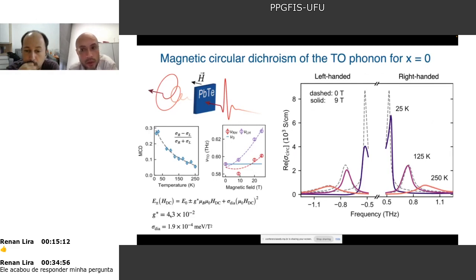So you can see here, still not very large, 4.3 times 10^-2, but much larger than the theoretical prediction from 2019 that I also showed you before. And here is the diamagnetic shift. This is the first experimental observation of diamagnetic shift of phonons, which is only possible to measure because of this very particular experimental setup that allows you to apply 30 Tesla, and then you can see this quadratic term.